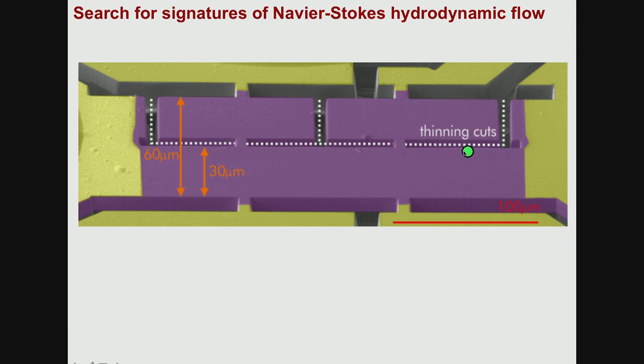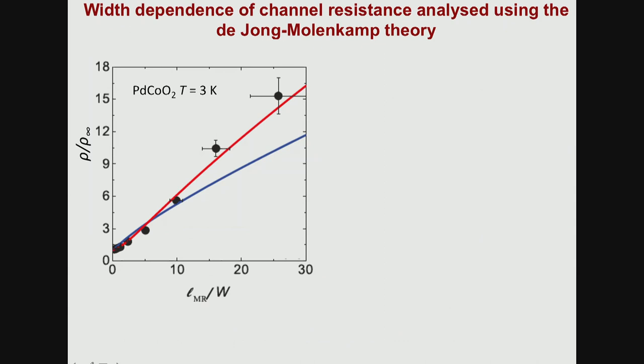We created a channel. We measured its flow resistance, in other words, its electrical resistance, for a certain width. Then we halved it, measured it again, then we halved it, measured it again, etc. And the results that we came up with were the following. So the red line is the prediction of hydrodynamic theory, and the blue line is the prediction of ohmic and then ballistic theory. And the data clearly look to be agreeing better with the red line than the blue line.